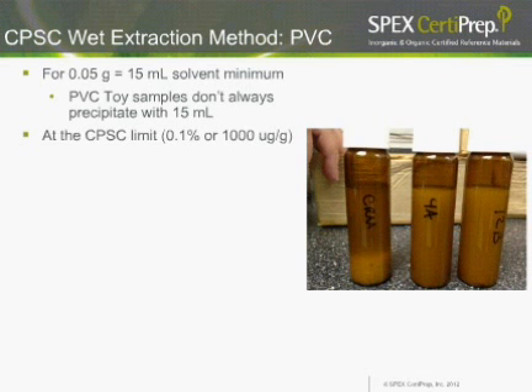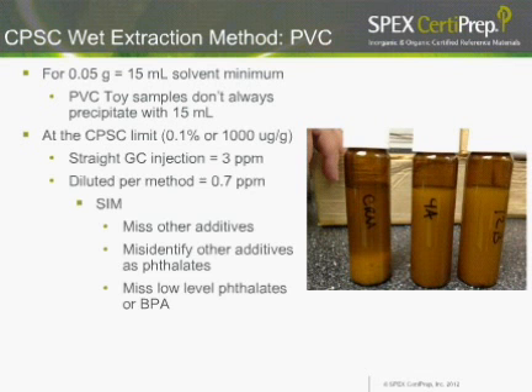So if you're looking at the Consumer Product Safety Commission limit, which is 0.1% of each of these phthalates, or 1,000 micrograms per gram, if you're injecting this 15 mils straight, you're looking at about 3 ppm on your GCMS. If you follow the method even further and you dilute it according to the method, you're looking at 0.7 ppm.